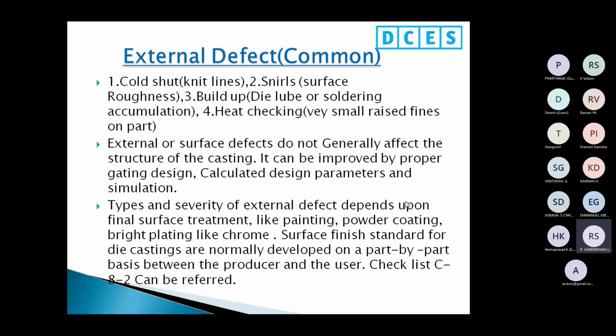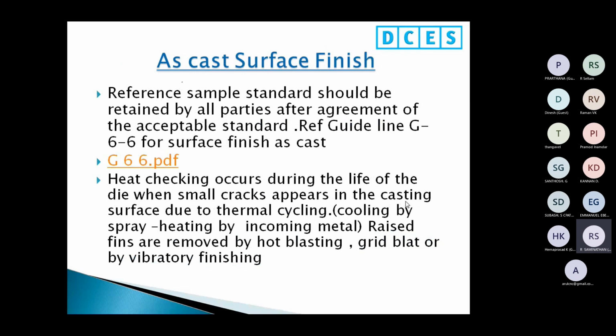That is external defects. External or surface defects do not generally affect the structure of the casting. They can be improved by proper gating design, calculated design parameters, and simulations. Types and severity of external defects depend upon final surface treatment like painting, powder coating, bright plating like chrome. Surface finish standards for die casting are normally developed on a part by part basis between the producer and the user. Checklist C82, already I showed you, can be referred. As-cast surface finish reference sample standard should be retained by all parties after agreement of the acceptable standard. Refer guideline G66 for surface finish as cast.